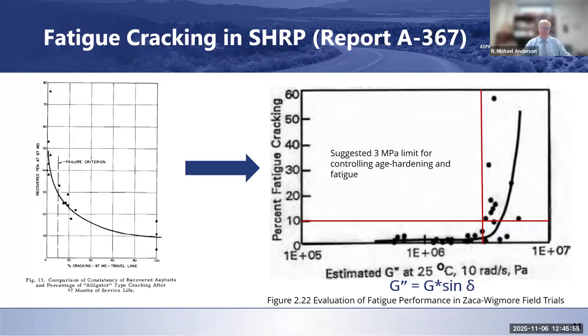Anytime you're going to larger strain tests, variability is going to shoot up. It's just natural. So you have to be willing to accept that if you're going to include it within a specification, it's about building it so that you're not making it impossible to consistently meet the specification. For now, I think mostly what we use are surrogates that we believe are related to things that will lead us to cracking. And that's why some of these parameters are surrogates for what we would expect to see for cracking. The other question had to do with bumping of the low temperature grade for RAP.